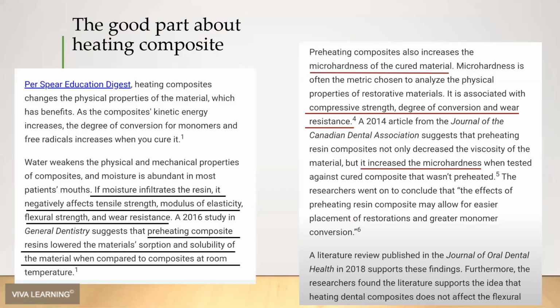The good part about heating composite, obviously, is there's a cool study here at Spear. It said that if moisture infiltrates the resin, it negatively affects the tensile strength, the modulus of elasticity, the flexural strength, and the wear resistance. So basically, moisture getting in the resin is bad. Preheating the composite lowers the material's absorption and solubility when compared to the composite at room temperature. So by preheating the composite, you're getting less chance of the moisture penetrating the resin, which is great. The other part is that it's going to increase the micro hardness. You're going to get a stronger composite and more wear resistance because you increase the micro hardness by heating the composite.